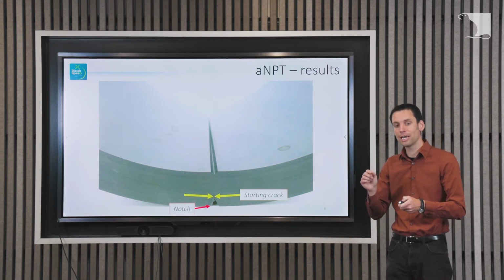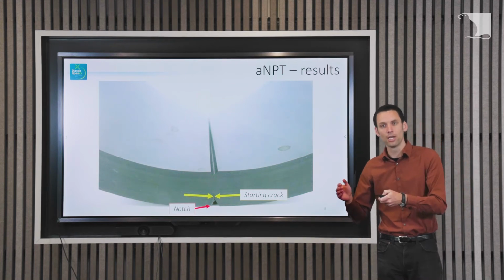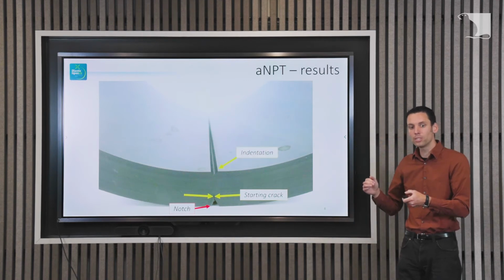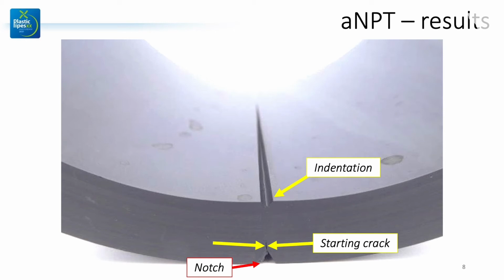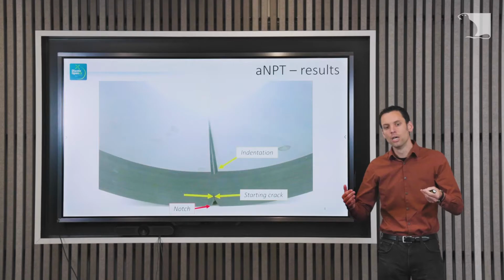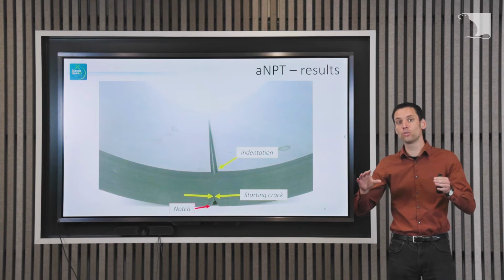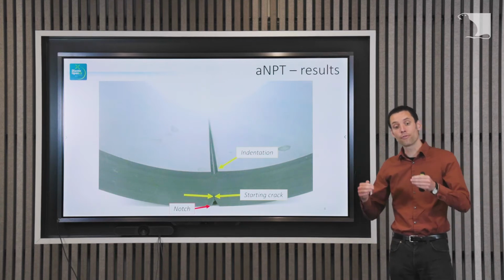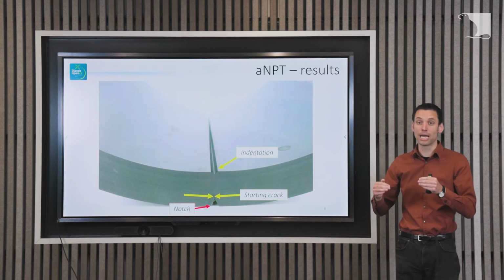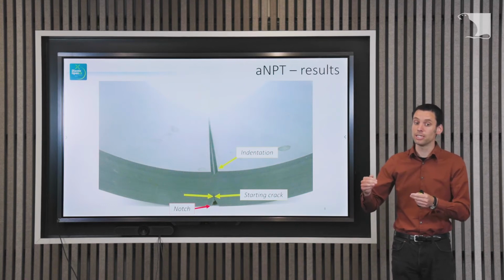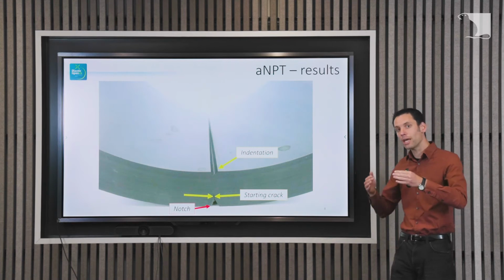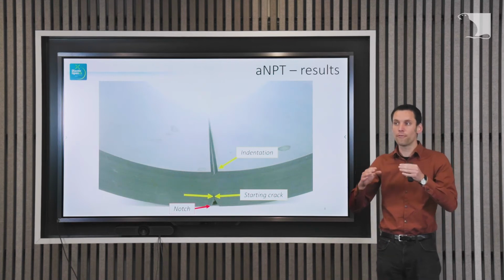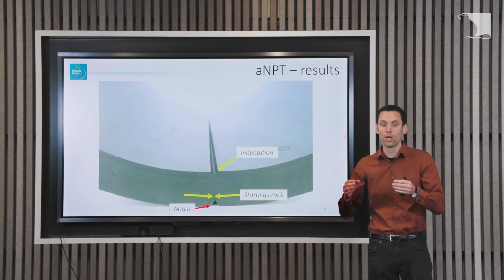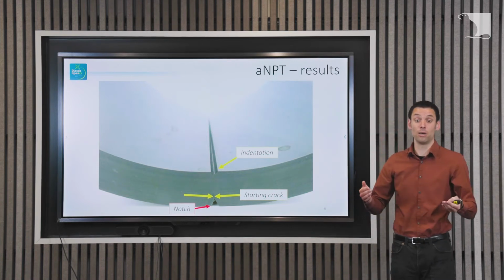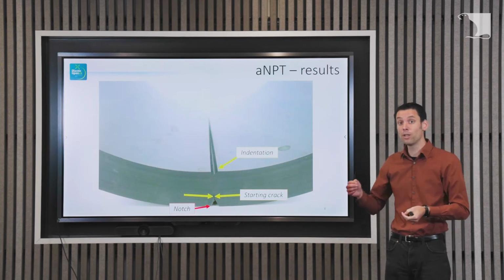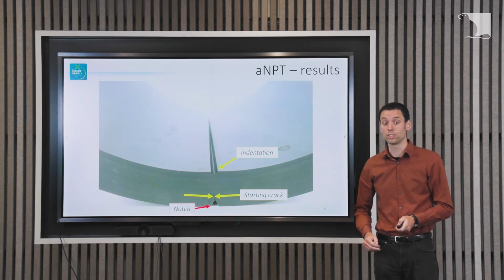Then we have that fine line again, and then something strange happens again, because on the inside of the pipe we suddenly see some indentation, some ductile flow apparently. A pipe wall has residual stresses due to the production, and we have compressive stresses on the outside and tensile stresses on the inside. So apparently, because the crack is starting, those stresses have to redistribute over the pipe wall, and therefore we get an indentation or some flow of material on the inside because of the residual tensile stresses.